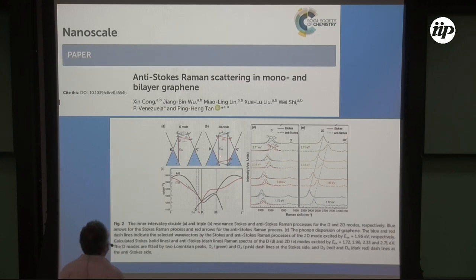So here, you excite the electron-hole pair. If you create a phonon, you lose energy, so you come to here. If you annihilate a phonon, you gain energy, so you come to here. So clearly, with Stokes and anti-Stokes, with one measurement, I measure two phonons, one here and another here. So that's the interesting thing. I think that's the main point of this paper, that show that with one measurement you can check two points in your phonon dispersion.